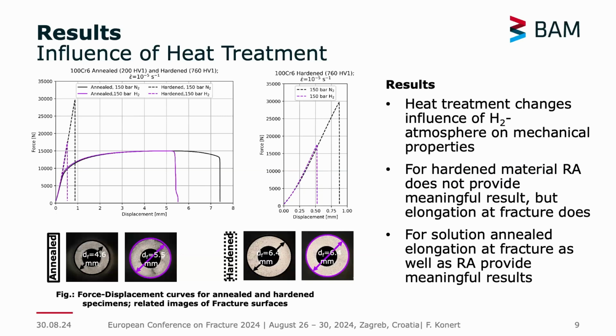So first of all, I also want to say something about the way you can interpret the results, because this is just one material, but in different microstructures. This is a 100Cr6 steel, one in the annealed condition and one in the hardened condition, tested under 150 bar hydrogen or 150 bar nitrogen as a reference. For the softer one, with a hardness of about 200 Vickers, you can see really clear ductile behavior. You have a lot of elongation in the force-displacement curve, but a clear loss in elongation when you go to hydrogen.